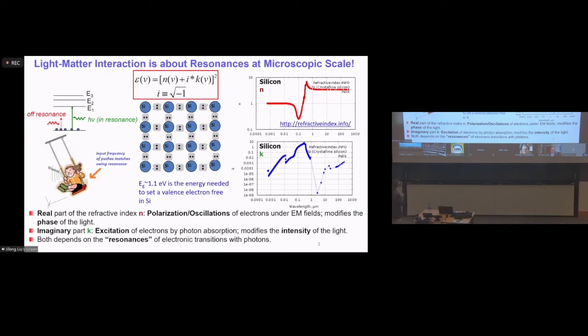The second part, the imaginary part, is talking about basically the dissipation. Essentially, you have some friction, you see some energy losses in the process. And that's due to the excitation of an electron from the ground state to excited states. And that part of the energy from the photon is being absorbed. And that introduces this imaginary part called the extinction coefficient.